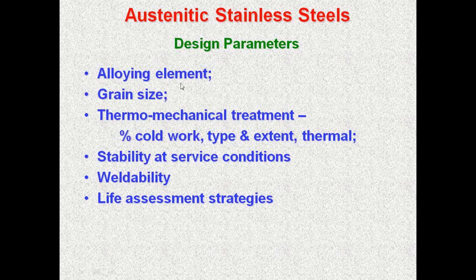The alloying elements that are present, particularly the impurity elements in minor quantities, their role is very important. Grain size, how fine it is, how coarse it is. The thermomechanical treatment that it has undergone, either during manufacturing or during fabrication, like percentage of cold work, type of cold work, the extent of cold work, the thermal treatment. Also the stability of service conditions. What are the temperature, load, the creep and fatigue conditions, creep fatigue interactions. The weldability, welding of these stainless steels is very important for making any component. Then the life assessment strategies.